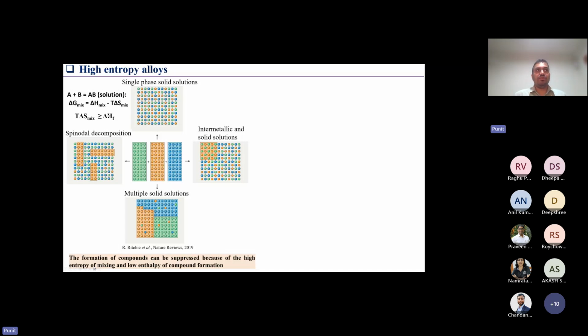And essentially you can see from this formulation that usually we refer to this single phase solid solution as high entropy alloys. But if you have possibilities of forming compounds, and in terms of having a higher delta HF, then in that case, instead of having a single phase solution, you might end up with this intermetallic and solid solution. So essentially high entropy alloys are not only high entropy alloys, they are also enthalpy stabilized alloys, where you have to carefully select these principal elements so that your enthalpy of forming these intermetallic phases is also minimized.